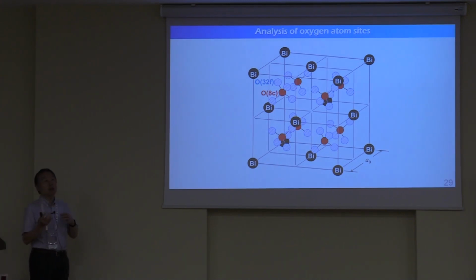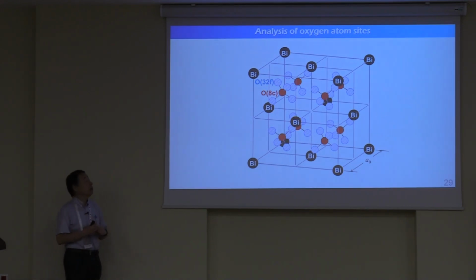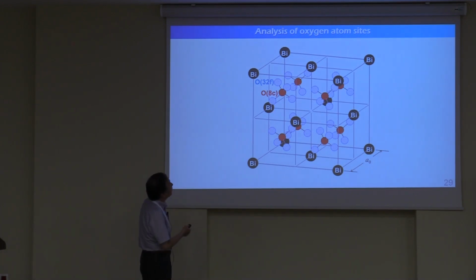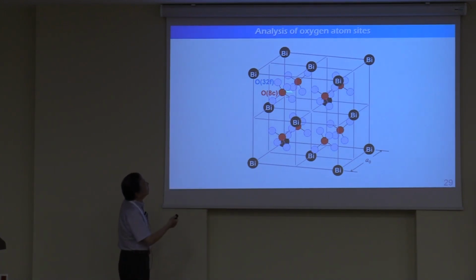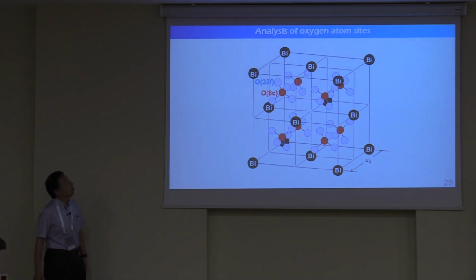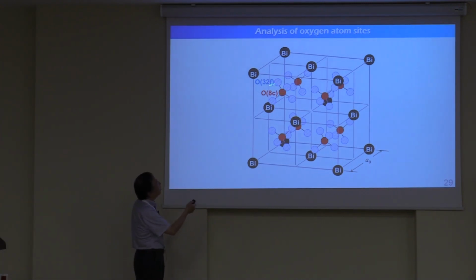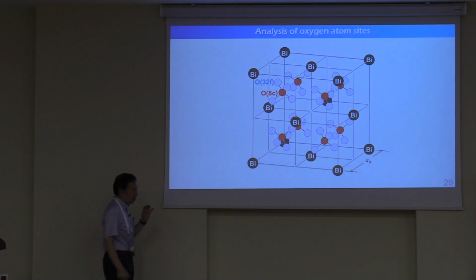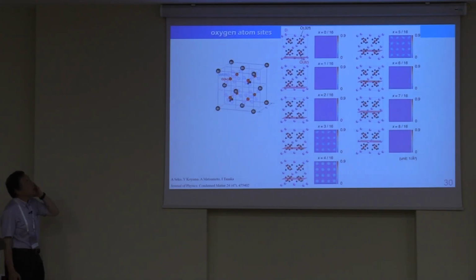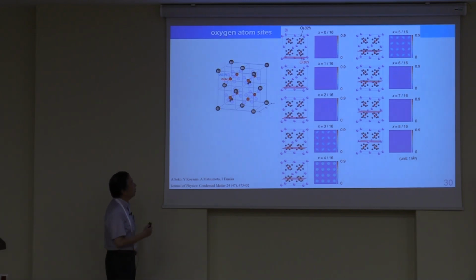Also, we can get some information on the diffusion trajectory, or how oxygen are moving within this crystal. This is a detailed examination of the bismuth oxide crystal, and oxygen are typically located in the center of this bismuth site, but there is another empty 32f site located like that, forming a tetrahedron. Actually, the oxygen is moving around within this 32f site, not in the other direction, but moving around within this tetrahedron. This is a result which shows that type of movement.